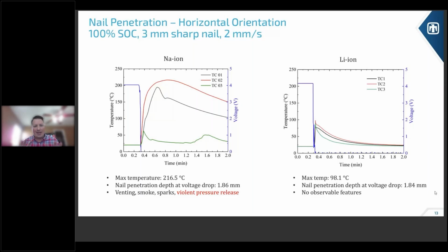So this slide layout is what I'll show for the rest of the destructive methods. The left side will always be sodium ion. The right side will always be lithium ion. The blue curve is the voltage, so you can see the point at which voltage was lost in the cell. And then the other colors are thermocouples that are attached to the outside of the cell, showing the temperature obtained. So for that nail penetration, the sodium ion got to 216 degrees, where the lithium ion got only to 98. Now, there's a bit of an asterisk here. NMC cells do tend to be pretty destructive under nail penetrations, but this cell was quite low in capacity compared to modern lithium ion NMCs. And so we believe that's why the lower temperature was obtained. Of course, you saw in the video, the sodium ion was quite destructive in its failure response. There was sparks, smoke, venting, and it broke itself free from that fixturing.